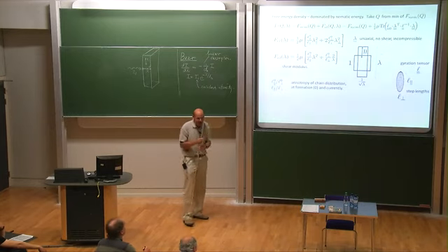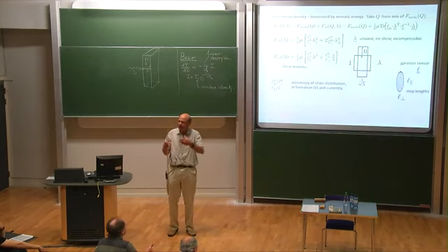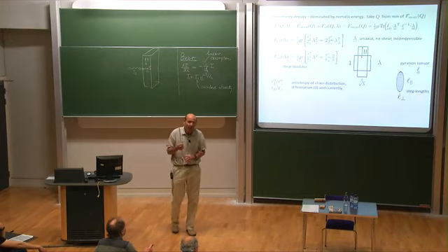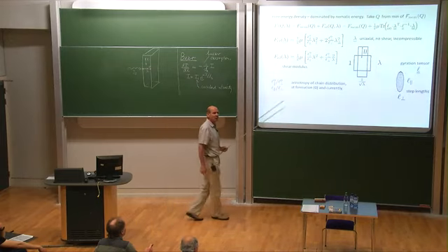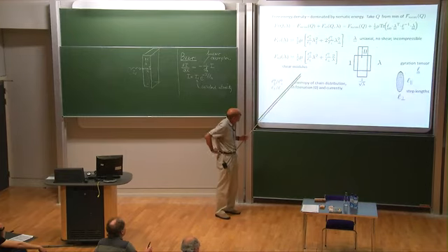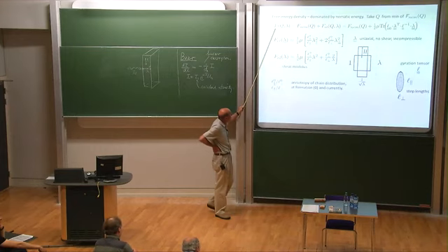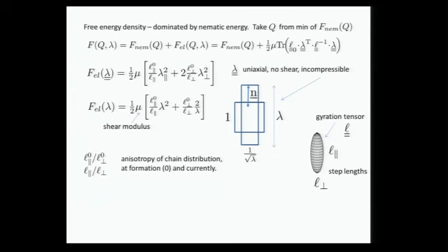Right, so I want to try and explain the buildup of this stress, and in particular the dynamics of the buildup of this, since it will determine the efficiency of this motor that I've talked about, and so it's quite important. Now, the free energy density of a nematic elastomer depends on the free energy density of the nematic liquid that it's really made up out of, plus a contribution which is due to the elasticity. Now, for elastomers, you can prove that it separates in this additive way. It's not obvious, but it can be shown.